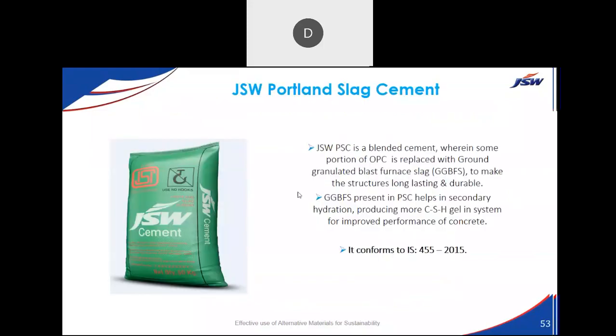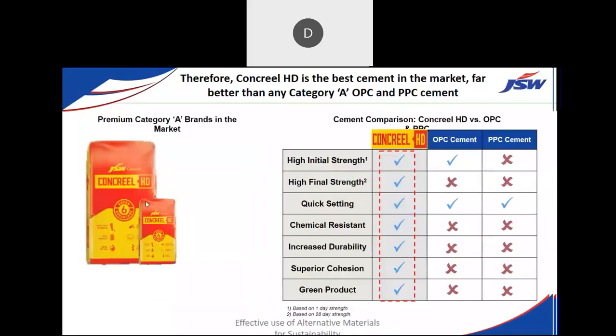So coming to the various alternative cements, JSW Portland slag cement has more than 50-55% slag in it, along with the clinker. A very eco-friendly cement. And one more eco-friendly cement is Concreel HD. It's a blend of OPC along with a lesser percentage of slag, with all the improved performance of OPC cement, using 45% slag in this. Especially the product is manufactured to give quicker early strength like OPC cement. Should not miss. People say, no, OPC is quick setting, I want to use OPC cement. But using slag cement also, you can make the concrete quick setting.